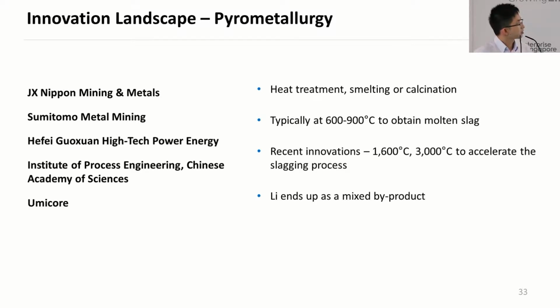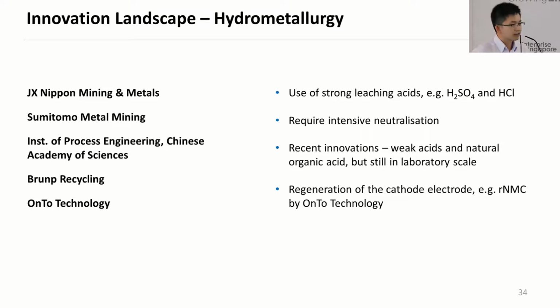Moving on, hydrometallurgy. So these are the top 5 again. It uses strong leaching acids such as sulfuric acid as well as hydrochloric acid in order to dissolve the cathode materials and recover the components itself. The use of strong leaching acids requires an intensive neutralization step downstream, where a lot of water or even alkalines will be required to neutralize them in the wastewater treatment plant. So in the recent innovations, we have noted the use of weak acids and natural organic acids to replace the strong leaching acids. So NTU is working on one project using methane sulfonic acid, which is one type of weak acid, and they're also studying the use of citric acid, which is derived from orange peels, as an organic acid. They are still working at laboratory scale.